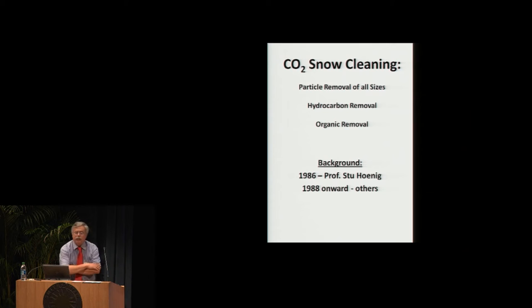Okay, CO2 snow cleaning is basically a very simple technique. Its unique abilities are particle removal of all sizes. We see particle removal from what's visible dust down to 3 to 5 nanometers, 30 angstroms, roughly 10 atoms across. At the same time, you can remove hydrocarbon stains like fingerprints, facial grease, organic residues. So it's a very simple, straightforward technique.